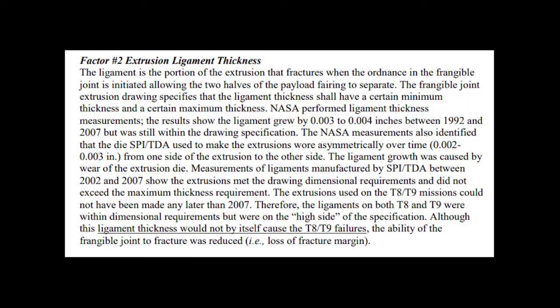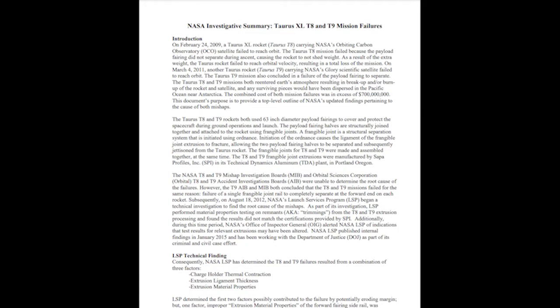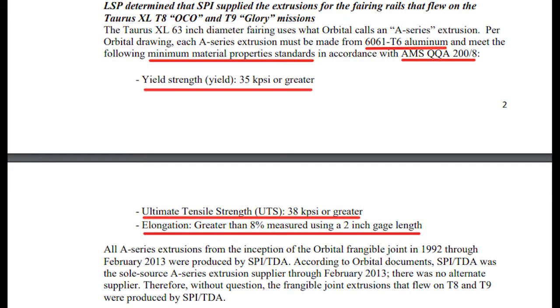In a public investigative summary released by NASA in 2019, NASA gives the material requirements for the two plates. The plates were to be made of 6061 T6 aluminum and are in accordance with AMS QQA 200/8 T6511 alloy. NASA required a minimum yield strength of 35,000 psi, a minimum ultimate tensile strength of 38,000 psi, and a minimum elongation of 8%. These values are comparable to some steels, maintaining the advantage of aluminum's weight.